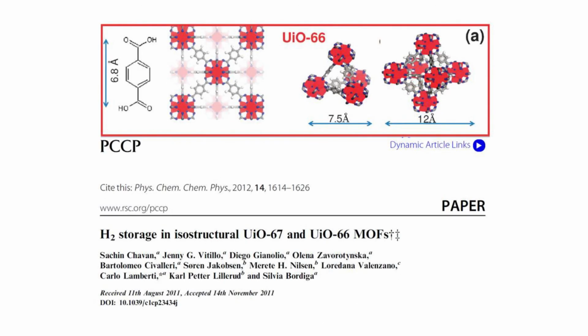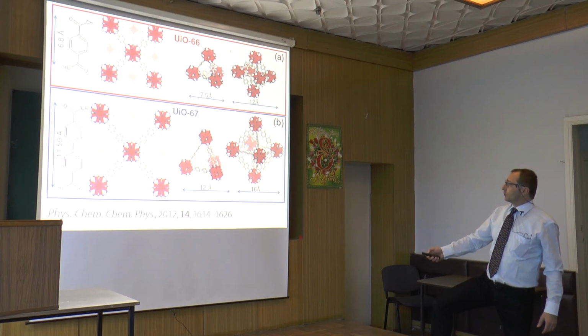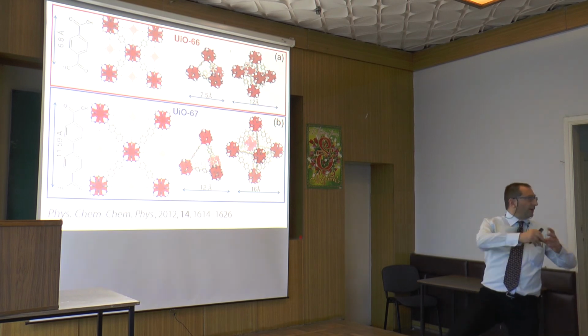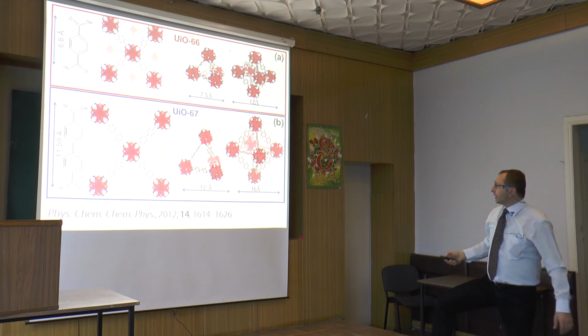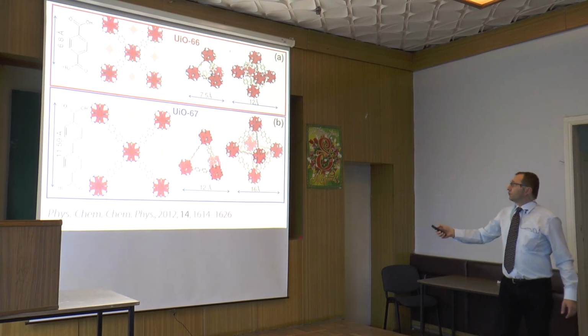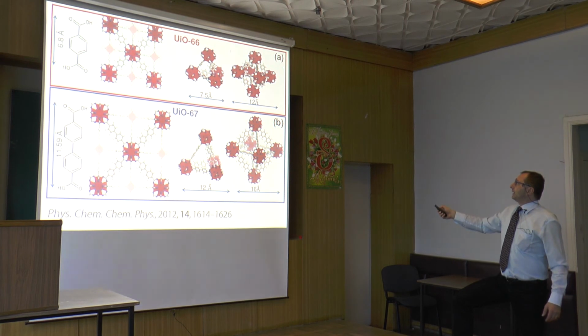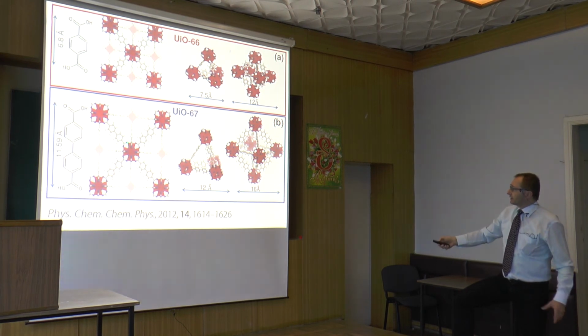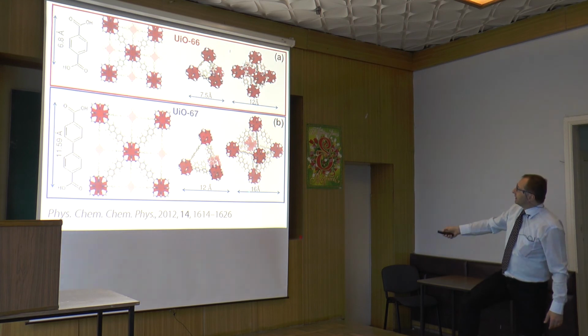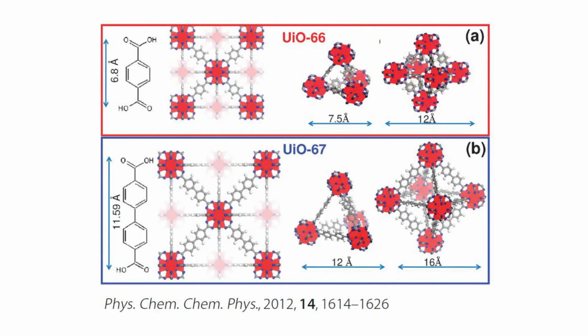Okay, then let's move to one application of this material, which is hydrogen storage. And here we will discuss these two homolog structures where we have the same inorganic cornerstones, and simply we double the length of the linker, changing the linker molecule. Of course we will have in this material tetrahedral and octahedral cavities, and in both cases the change of ligand will bring an increase of internal volume from 7.5 to 12 Angstrom and from 12 to 16 Angstrom. So you will have more internal volume available that can be used for molecule storage, in this case for hydrogen storage.